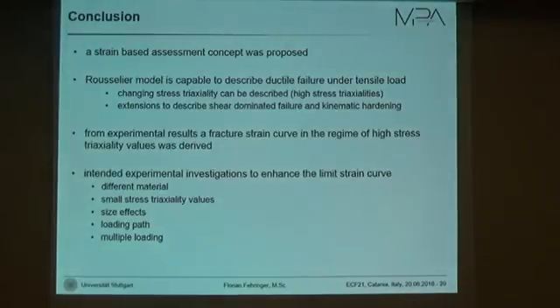So the conclusion: at first I showed a possible strain-based safety assessment concept, and then I showed the capability of the Rousselier model, which is able to describe material behavior for high stress triaxialities and changing stress triaxialities, but which needs some extensions to describe shear dominated failure and kinematic hardening behavior. A fracture strain curve we could derive from the experimental results in the regime of high stress triaxialities. And on the last 2 slides, I showed our intended experimental investigations to enhance our limit strain curves by influences like material, stress triaxiality, size effects, loading paths, and multiple loading situations.